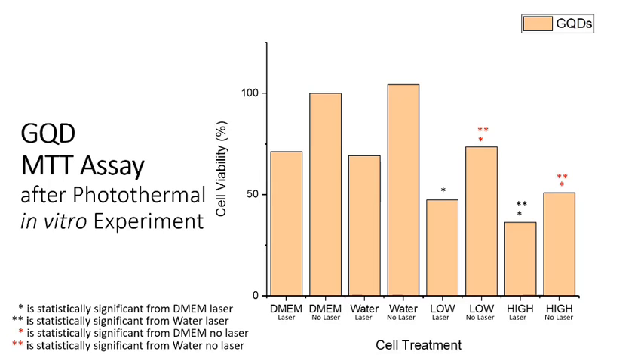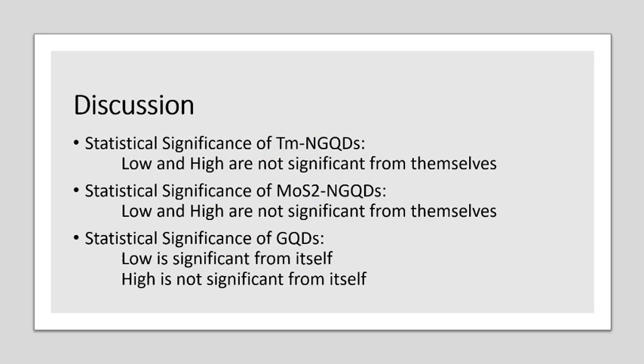So keeping in mind these 4 bars right here on each of the graphs, we look at the statistical significance between the low concentration that was irradiated with the laser and wasn't irradiated with the laser. And then we also look at the significance between the high that was irradiated with the laser and the high that wasn't. So what we're seeing with the thulium is that the low concentrations, neither of them are significant from each other, and the high are not significant from each other. So that's telling us that there's not really anything we're seeing from photothermal properties. Otherwise, the laser concentration would be much worse.